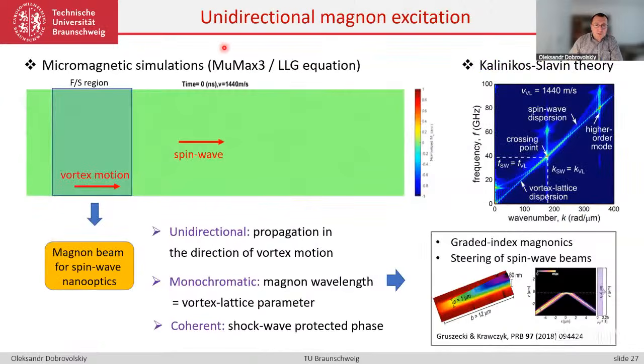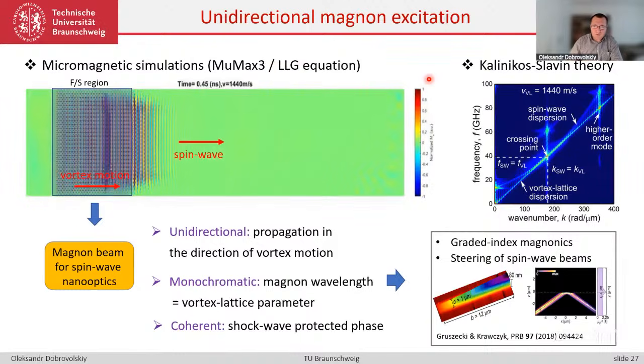I'm moving to some interpretation with the help of analytical Kalinikov's line theory to show that there is a joint crossing point in the dispersion of both Fluxons, linear characteristics, and Magnons, parabolic characteristics, with this very bright area corresponding to the strong interaction, so crossing of the two dispersion characteristics. Micromagnetic simulations based on the solution of Landau-Lifshitz-Gilbert equations support these observations.